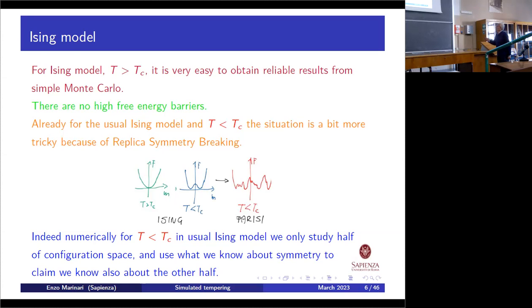So when you start your Monte Carlo, typically, you just study half of the possible phase space, okay? But you say, fine, there is a symmetry. So you know exactly what happens in the other half space. So you don't do well the Monte Carlo when you are in a broken phase of an Ising model, but you don't care because you know the results in the other part, okay? So numerically, for this model, you only study half of the configuration space and use what we know about the symmetry to claim, because it's true, that we know also about the other half.